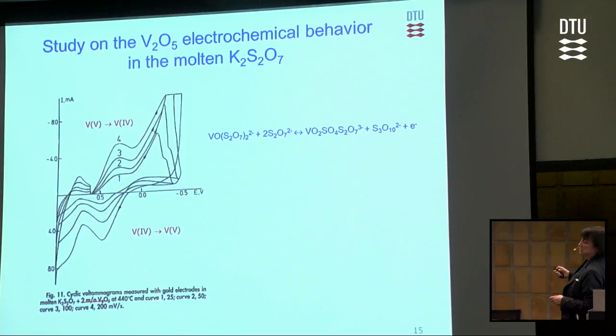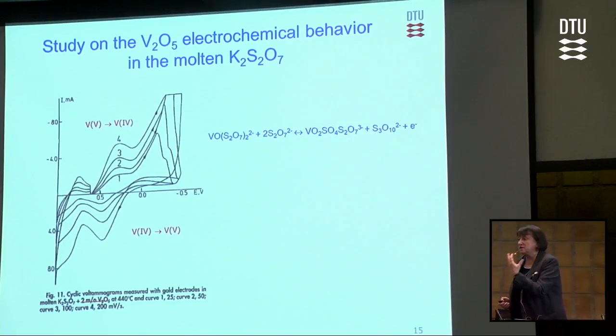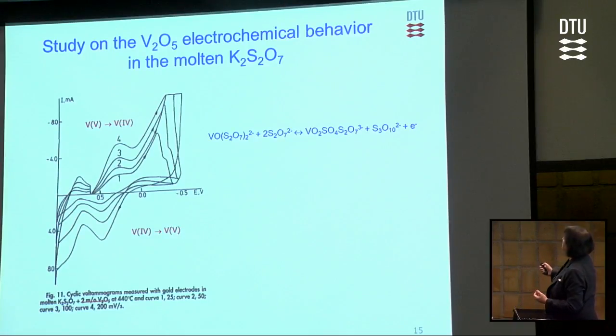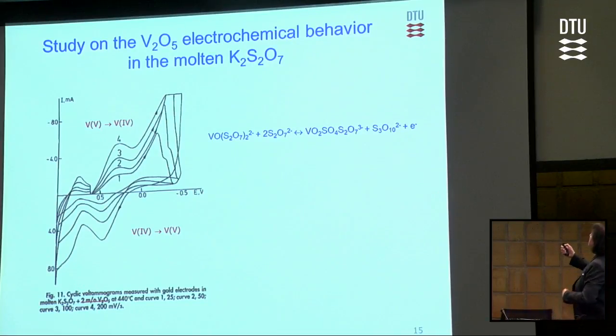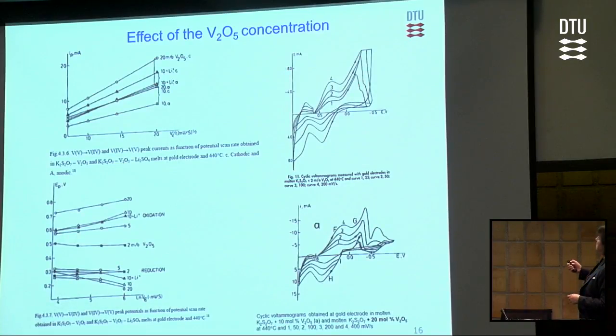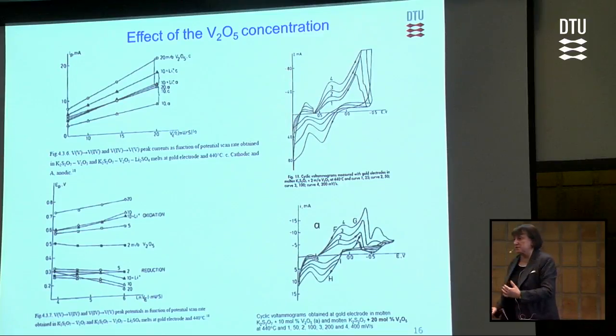So I have found these well-defined cyclic voltammetric waves, which are responsible for reduction of vanadium and oxidation of vanadium. If you ever use cyclic voltammetry, it's a classic reversible electrochemical reaction, where the peak potential is not a function of potential scan rates. It's only for 2 mol% of vanadium pentoxide. That's the reaction. So what I have found is that an increase of composition has a negative effect on kinetics.